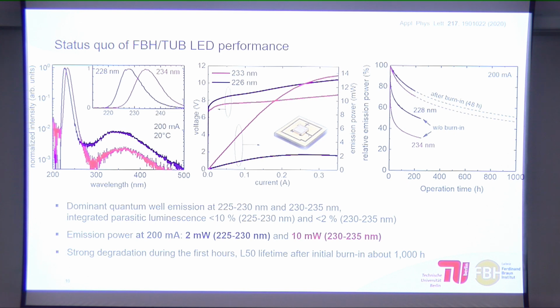So at 228 nanometers, we have around 10% parasitic luminescence. So unlike a conventional lamp, we don't have a discrete emission wavelength. We have a wavelength with a full width at half maximum of around 8 to 10 nanometers, but you have also parasitic luminescence at longer wavelengths. But if you remember, there's a logarithmic scale. But it is, for example, for disinfection of skin, this could still be a problem. But for many applications, the big difference in the intensity is no problem. This is 10%, like I said, for 228 nanometers, and at 234 nanometers, we have a parasitic luminescence of around 2%.